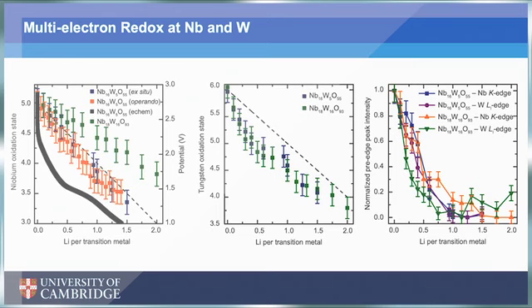And so when we look at this together, what we see is that both the niobium and the tungsten are reduced in parallel, not sequentially. So they're both fully participating in the redox process at all states of charge. And they're both participating in multi-electron redox. So as we get up to high amounts of lithiation, so above 1 lithium per transition metal, we are still seeing reduction in both the niobium and the tungsten.